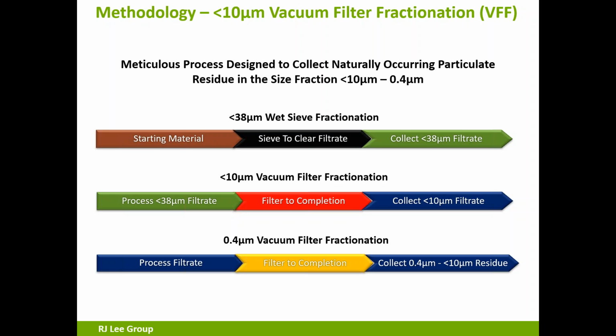Now we're going to filter that onto a 0.4 because we don't care about anything below 0.4. If you remember the slide on respirable particulate, IARC told us that anything below 0.4 is irrelevant, and they're absolutely right because that gets into Brownian motion and you actually cannot inhale down to the deep lungs anything below a certain size because it won't move in the air. This is one of the issues with nanotechnology. So we're going to collect that fraction between 0.4 and less than 10.